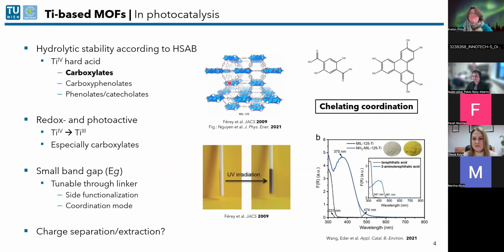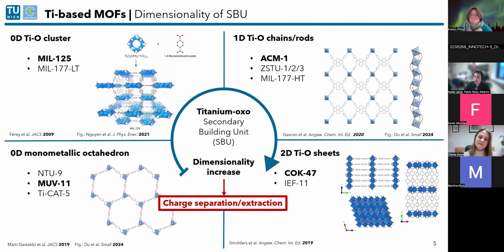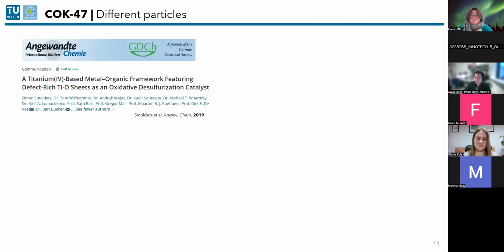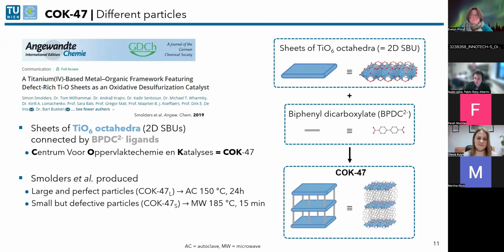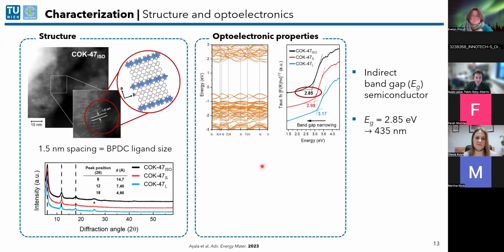Okay, we have more questions in the chat. From Fatima: what is the effect of the porosity of the MOF COK-47 on the yield of the reaction? And what pore size is recommended for MOFs used in photocatalysis? Very good question. These were very small pores, and actually we couldn't find them properly, even in the samples that had missing linker defects. So my way of viewing this particle is that it is actually not really porous. And the ones that we made porous by introducing defects also didn't show any advantage.